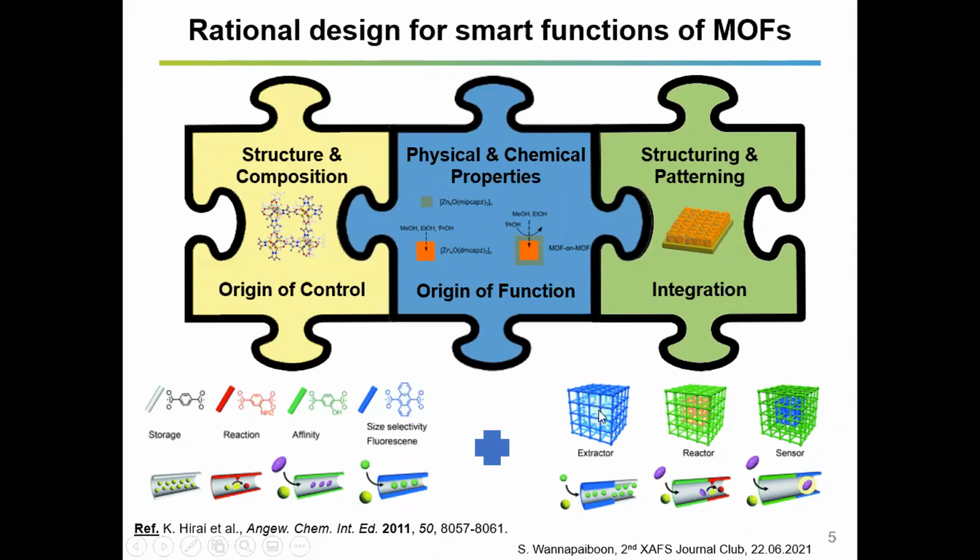We have a large pore inside that behaves as the storage part, and the other MOF has a smaller porosity or pore opening window for size selectivity on top of that storage part, which behaves as the selective part, so that only some molecules are stored inside the porous material and molecules with bigger size or different functionalities or characteristic properties are left out of the structure.